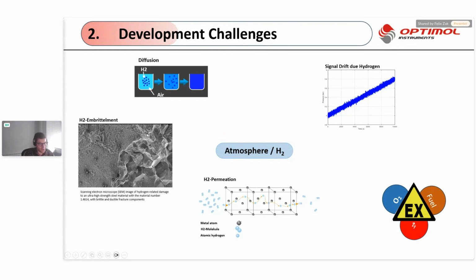This means, due to Graham's law, which tells us that the diffusivity of a molecule depends on 1 over the square root of the molar mass. So this is why hydrogen is very diffusive. Also, due to the low energy that is required, hydrogen dissociates on the surfaces to atomic hydrogen and then permeates through the material, and can also accumulate there,